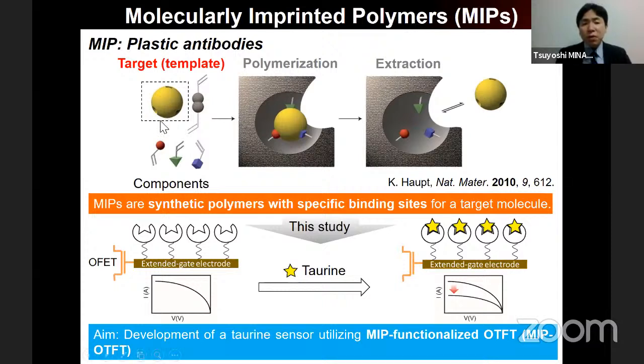In this case, the yellow circle is the target molecule. There is a component of the monomer unit, and it can bind to the target molecule. If we mix the target molecule and such a component before the polymerization, we can make a complex. After we fully polymerize, we can remove the target molecule. After we remove the template, a hole exists in the polymer. Using such a hole, we can selectively detect the target molecule as a sensor unit.